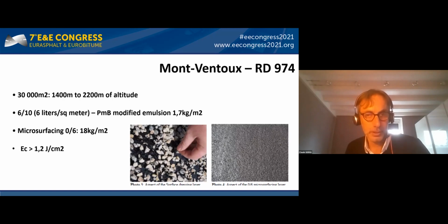First, the Mont Ventoux in the south of France. A section of 30,000 square meters was applied on the RD 974. This road is access to the ski resort of the Mont Serein at 1,400 meters of altitude. The climatology of this road is also very atypical, with temperatures that can be hot in the summer, but also very strongly negative in the winter at the summit, with violent snowfalls that require the passage of a snowplow.